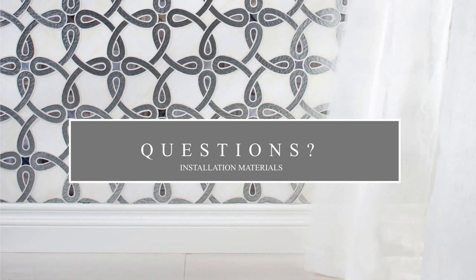So we have a question, is epoxy grout sometimes too strong for certain glass tiles? And what you're referencing is our longstanding recommendation not to use epoxy. And yes, there can be certain situations where a true 100% solid epoxy is not a good choice for glass tile, particularly in exterior applications with large format tile. So as the glass tile expands, because the epoxy has such high compressive strength, it doesn't allow it to move and it can become problematic. It can cause debonding or cracking.